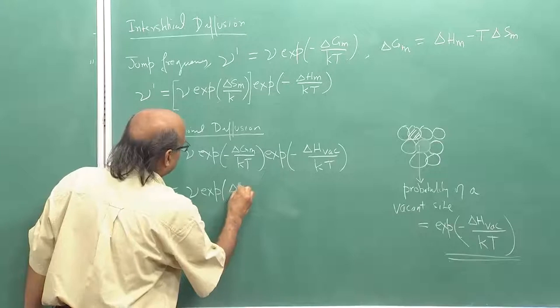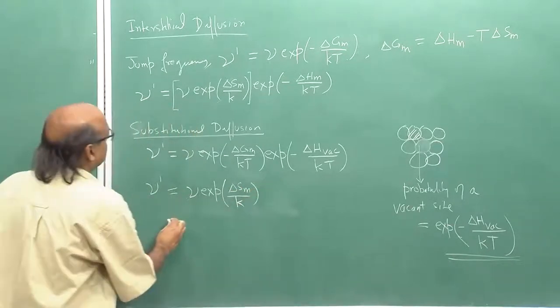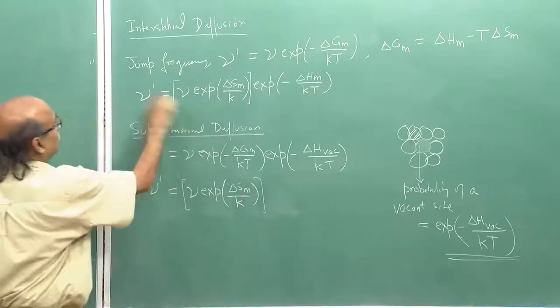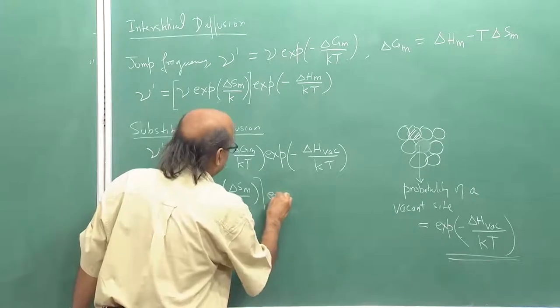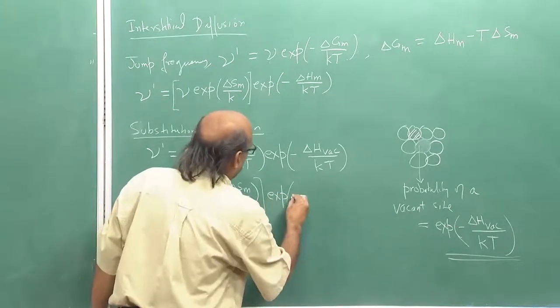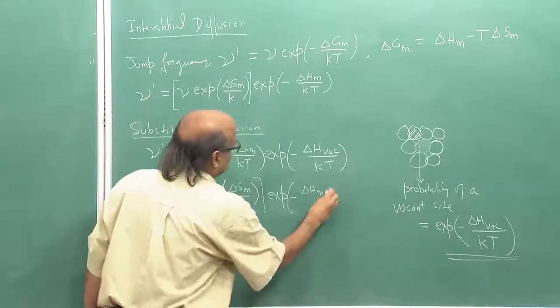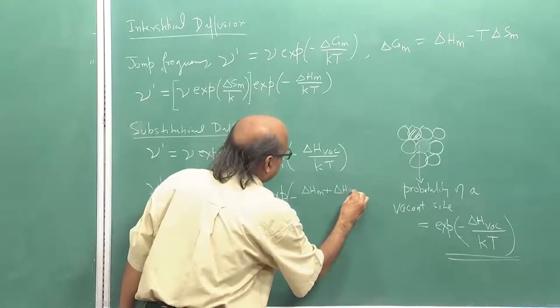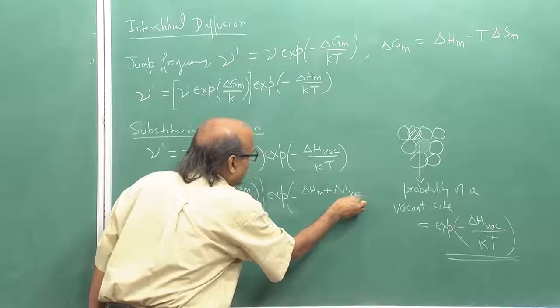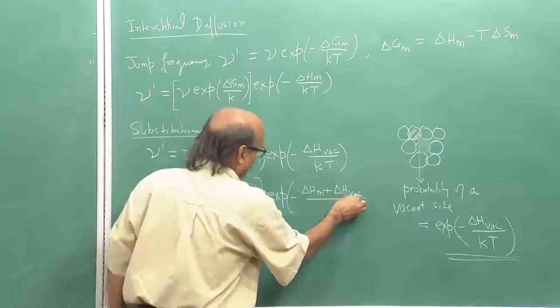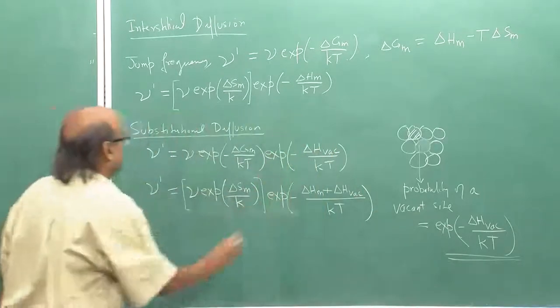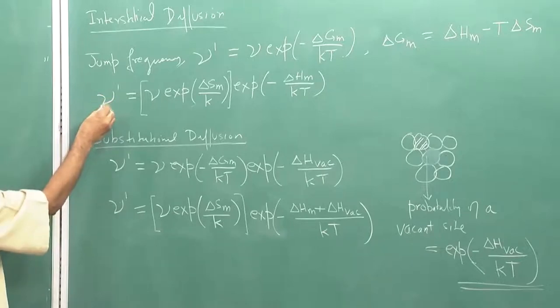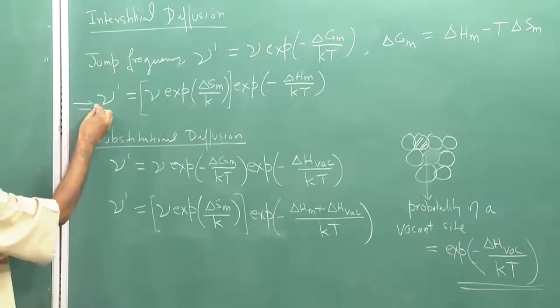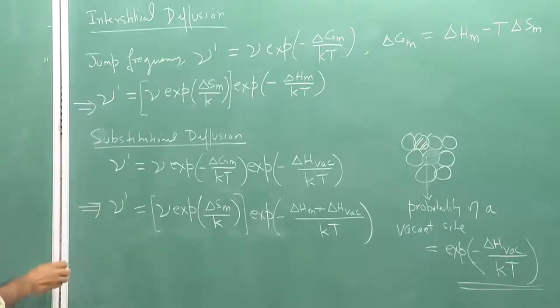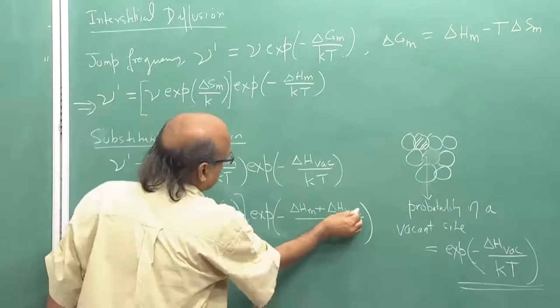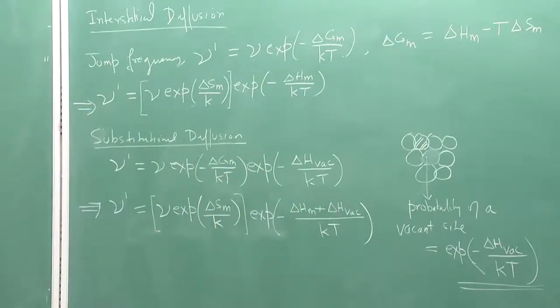For substitutional diffusion, the jump frequency would become nu exponential delta Sm upon k, the temperature independent terms, as in the case of interstitial diffusion, times exponential minus delta Hm, and there will be an additional term, an additional enthalpy term, the enthalpy for creation of a vacancy. So, delta Hm plus delta H vacancy divided by kT. So, you can compare the relationship for jump frequency for interstitial diffusion and in the case of substitutional diffusion, the additional difference is simply the enthalpy for creation of vacancy.